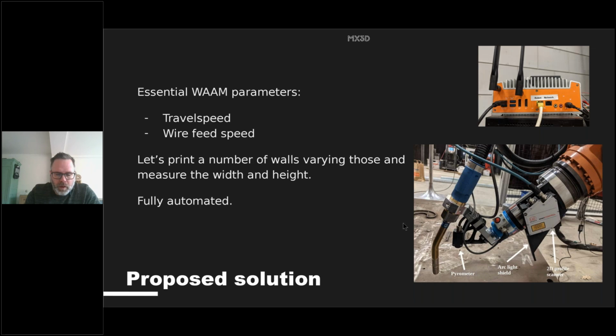Our idea was to print a number of walls, each with their own parameter set, and to measure the resulting properties, all automated. The two most important factors for controlling the weld are the travel speed and the wire feed speed, so we decided to focus first on these two, but with our solution it should be trivial to vary other parameters as well. Since the interpass temperature is an important aspect for reproducible weld shapes, and WAAM parts tend to get pretty hot, we included a pyrometer as well.